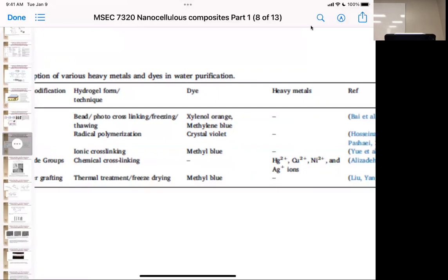So in high concentrations, copper is also a contaminant. But notice they're bidentate, which means once they get in there, they're going to be bonded to one hydroxyl over here, and you can't get it out. It's going to be irreversibly bound into the system. And that's the benefit of having these hydrogels, because you have so many hydroxyl groups on there, and you also have tons of hydroxyl groups on the surface of your nanocellulose, crystalline nanocellulose.